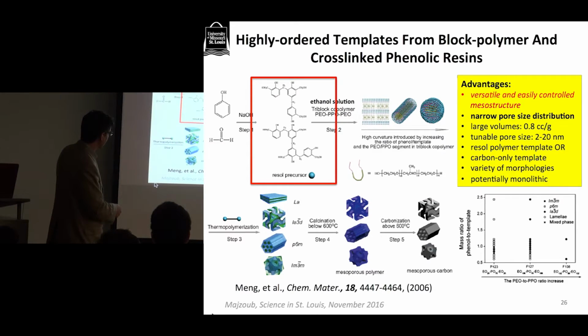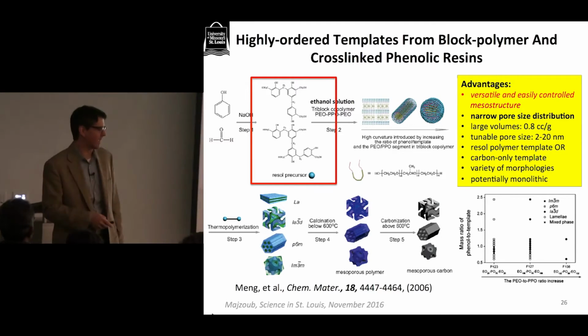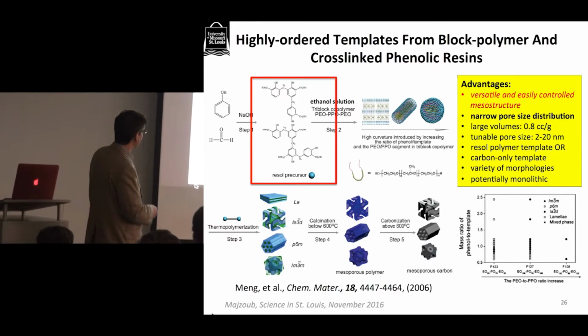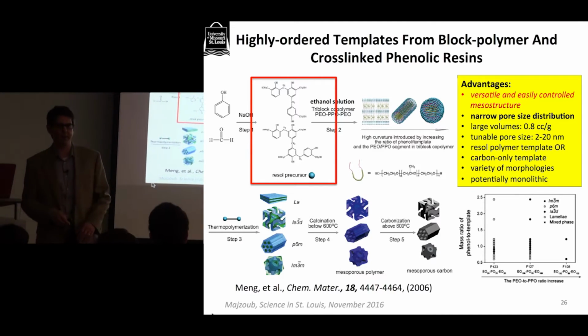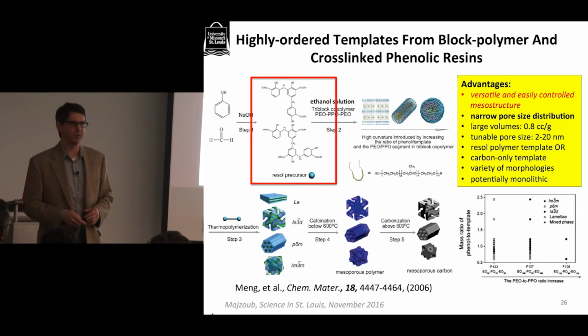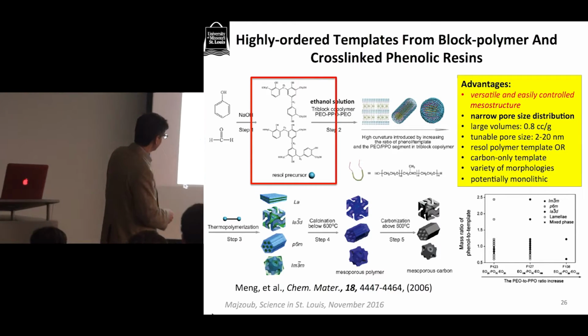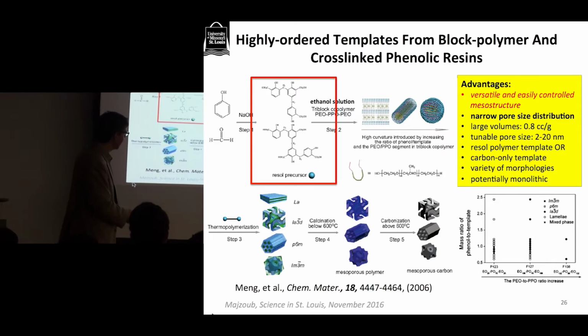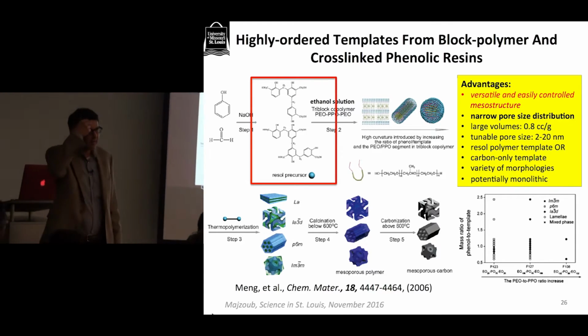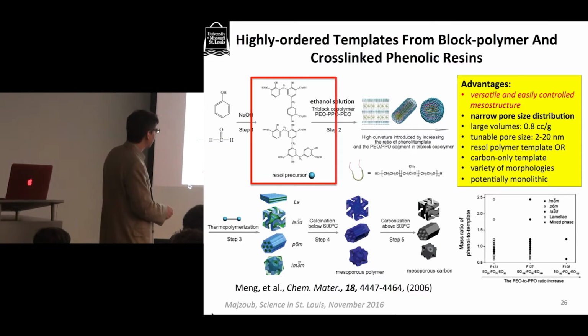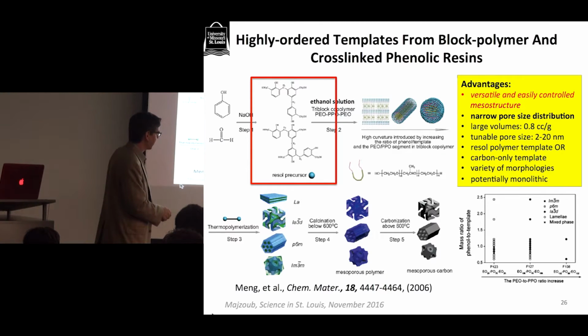And so the pores here, I'm showing some pores here in these little hexagonally packed cylindrical pores. These pores can be made anywhere from 2 nanometers to 10 nanometers, say. So with this material, there's a lot of stuff in here at the moment because we haven't gotten it hot yet. But we can simply put the material now into an oven, and we can bake it until we just cook everything off, except we leave only the carbon. And to do this, you have to go to temperatures anywhere from 600 to 1,000 degrees centigrade, which is very hot. But it leaves you with a very clean, porous network or framework.